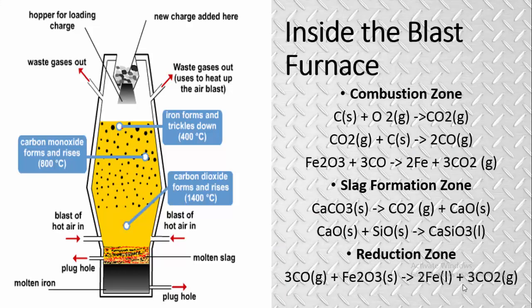So, all this, that is the hematite ore, the limestone, and the coke, are collectively called the charge. This charge is fed into the blast furnace continuously, and 1 ton of iron requires approximately 2 tons of iron ore, 1 ton of coke, half a ton of limestone, and 4 tons of air. Hot blast stoves and powerful blowers force huge amounts of preheated air into the furnace. Heating the air increases the production and decreases fuel consumption. In striking contrast to the primitive methods, the modern blast furnaces are controlled scientifically. Up through the mass of coke, iron ore, and limestone is blown a roaring blast of preheated air.